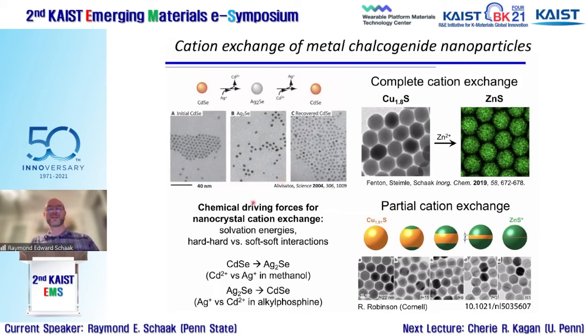And so, I know this is a very broad audience. I'm not going to dive in deep on the chemistry. I'm just going to say this is very elegant chemistry because the reactions that are happening in the nanoparticles are driven at least in part by chemistry that's happening in solution. These are all colloidal nanoparticles. They're dispersible in a solvent. And you can basically dial in what reactions you want to happen based on fundamental chemical principles like solvation and coordination and hard soft acid base theory and things like that.